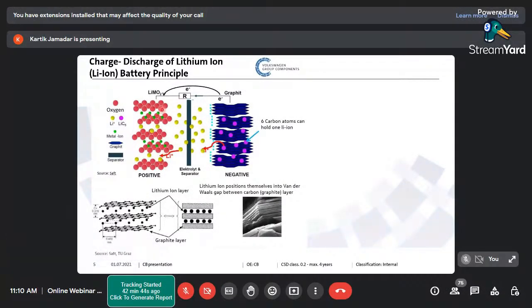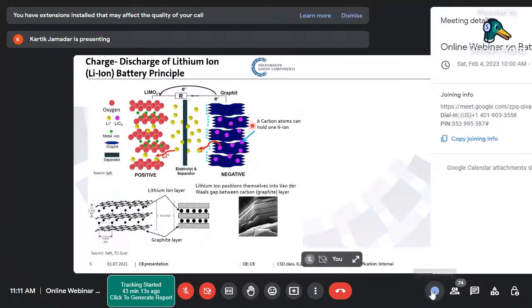On the cathode side, nothing had changed. The same metal oxide was there, and the metal oxide was basically holding the lithium. The only difference was that now our source of lithium was the cathode. It means when I'm making the battery, my lithium is not on the anode side, it is on the cathode side, and this cathode has both metal oxide and lithium. This lithium needs to be transported from cathode to anode during the first charging process, and that is done by the manufacturer. So they shift this lithium from the metal oxide to the graphite, and since there is no metal, the lithium is intercalating deep inside the graphite electrode.